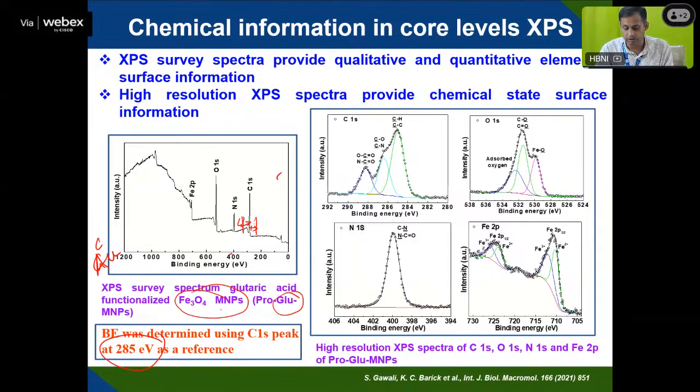You can see here this is Fe3O4 nanoparticle coated with amino acid. This nitrogen signal is highly symmetric. This is the iron signal. This is the oxygen and carbon signal. You can see here the carbon is fitted into 3 lines. The carbon-hydrogen, the stoichiometric carbon in the material, the coating agent or atmospheric carbon will be here at 285.0, and then carbon-oxygen, which has high electronegativity, and nitrogen; oxygen and nitrogen are both here.